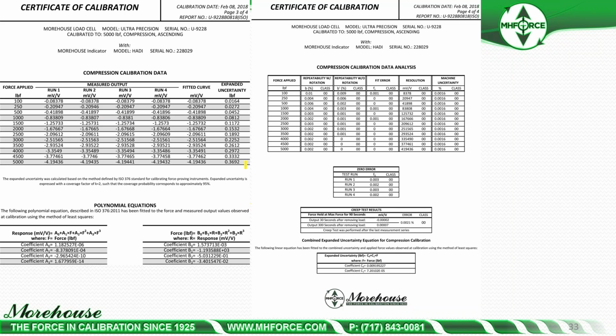Looking at the data in more detail, here's more information, compression calibration data on our CERT, polynomial equations. ISO only allows up to a 3rd degree, so that's all we can use. They may be better at a 5th degree, but it doesn't allow it. And then the page 4 of the CERT has all the classes. And if you look through here, you can see repeatability with rotation. Here's all class 00, repeatability without class, fit error, resolution. It tests for resolution, uncertainty of the machine, class 0, zero error down here, all 00s, creep, all 00s.